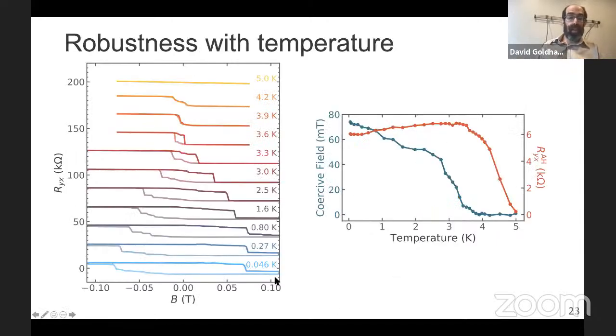And in fact, the magnet lasts up to 5 Kelvin in terms of the anomalous Hall signal, and up to about 4 Kelvin in terms of having a hysteresis loop. So I plot here the size of the anomalous Hall signal, this step in the Hall signal, and it stays robust out to about 4 Kelvin, and then drops off rapidly. And the coercive field, the field it takes to flip the magnet, drops more steadily and becomes 0 at 4 Kelvin. So these don't require the millikelvin temperatures to see, but they are of course still low temperature.